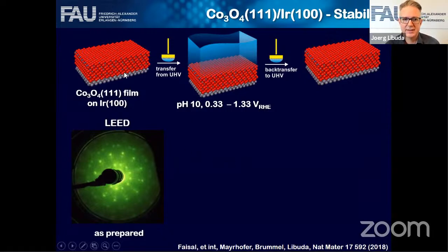So this is an example. This cobalt oxide film that we make in ultra high vacuum, and typically the surface scientist looks at the structure of such films by doing electron diffraction, LEED. In LEED, you see a very characteristic diffraction pattern that tells you that the surface is ordered. It's well defined, you are happy, and then you bring it into this hostile environment of an electrolyte. And you can do experiments there.